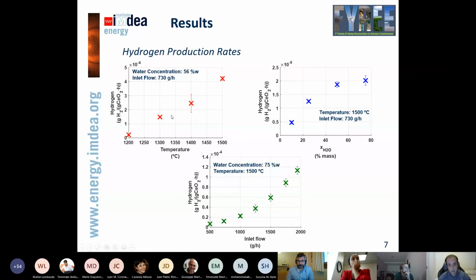Here, what we see for the first test, for hydrogen production in the temperature test, is that when we increase the temperature, we also increase the hydrogen production. That is something that we thought is normal because of the reduction extent of the material, the vacancy concentration. The higher the temperature is, for the same concentration of both water and oxygen, obviously there will be more vacancies available for the water to attack and produce the hydrogen.